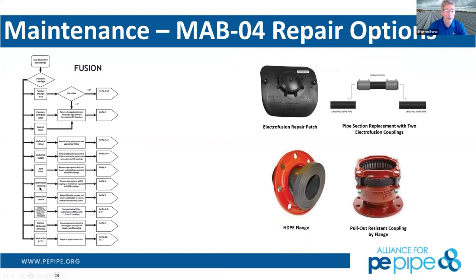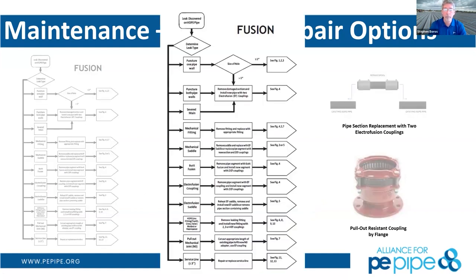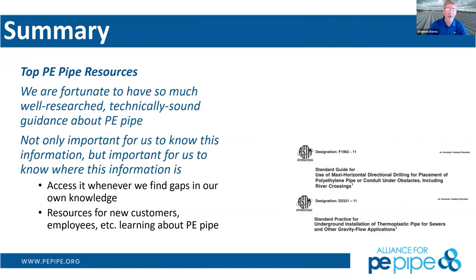What type of repair do I want to do? Mechanical fitting, electrofusion, and then it'll step you through the process. If you do this, I have to remove the pipe segment with butt fusion and install a new segment with 2 electrofusion couplings. There's your repair option for this particular situation. So you don't have to know everything about it. It's going to step you through there and give you the most logical and reasonable repair option that's available to you. And you can see there's a multitude of repairs: electrofusion repair patch, electrofusion coupling to put a new pipe spool piece in there, or a flange adapter if you'd rather just go to a flange after that, or a fully mechanical coupling with full restraint pullout works just as well also. The same thing we just went through, trying to hurry up a little bit.